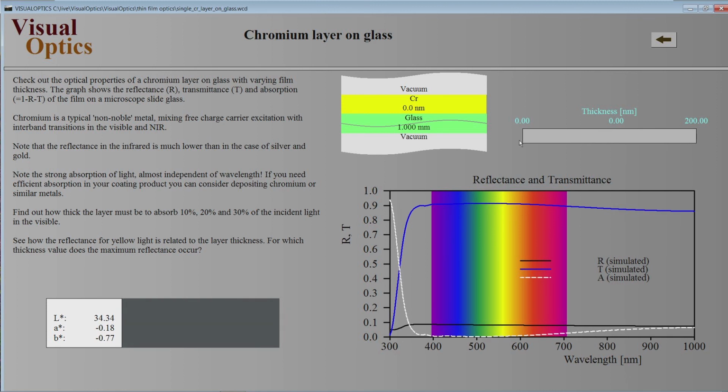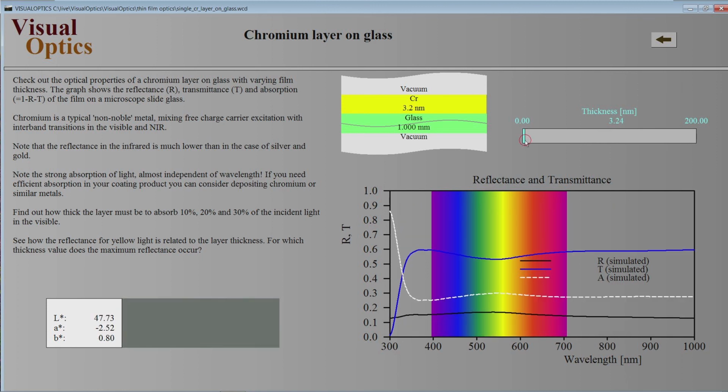Sometimes this strong absorption is not wanted. I will discuss in another tutorial the properties of glass coatings, where nickel chromium layers or titanium layers are sometimes used as so-called blocker layers, and if they would not be oxidized, they would absorb a huge amount of radiation, which would destroy the positive properties of those coatings.